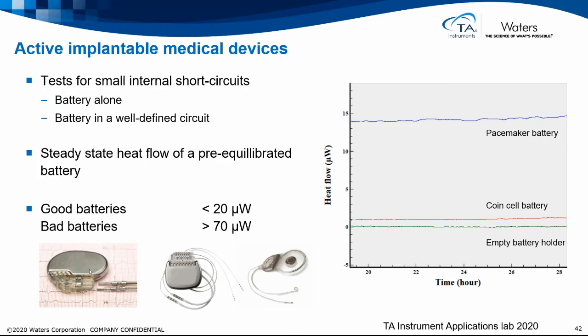Typically, this measurement is done as steady state heat flow of a pre-equilibrated battery. So it's equilibrated at 37 degrees and then put into the calorimeter, you measure heat flow and remove it. On the scale here, we measured for a long period of time, but usually it's just steady state and out of the calorimeter and test the next battery. Good batteries should have below a certain level of heat flow, and bad batteries, if there is a short circuit in the battery, will give off much more heat.